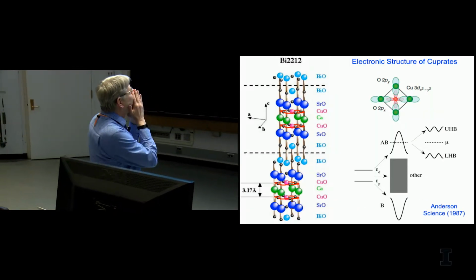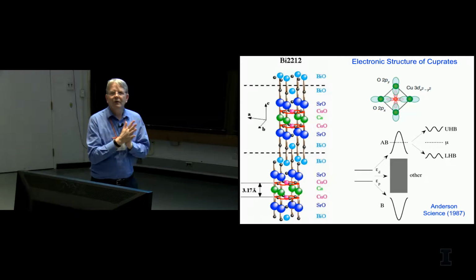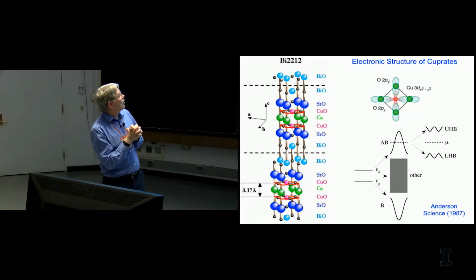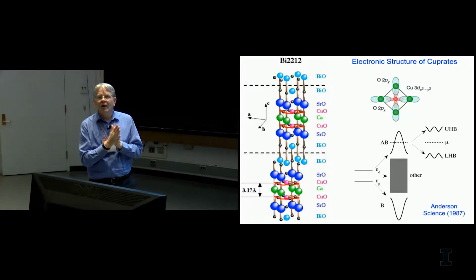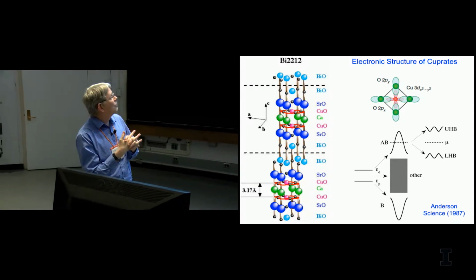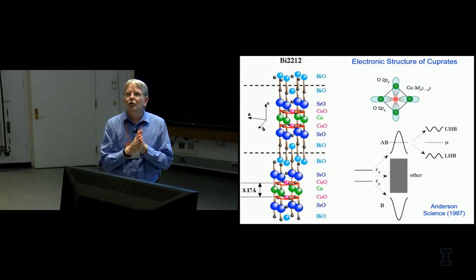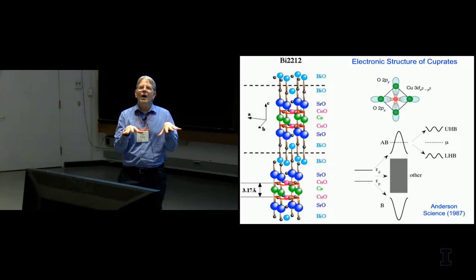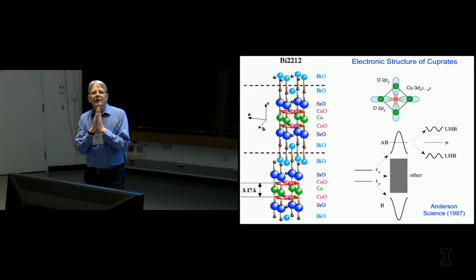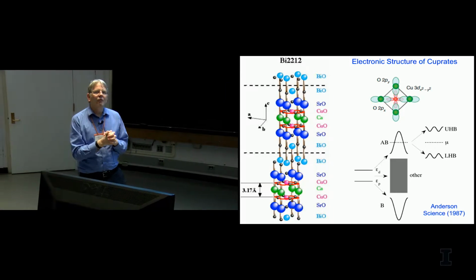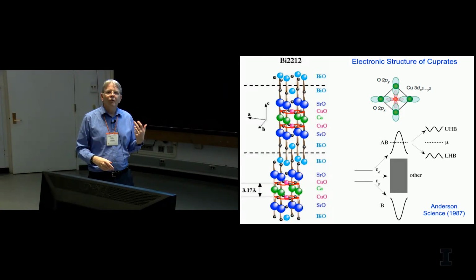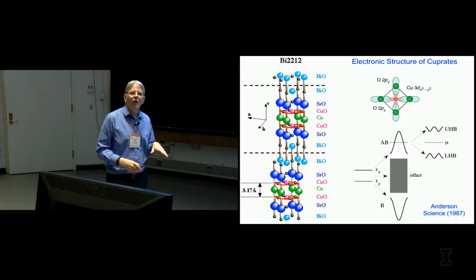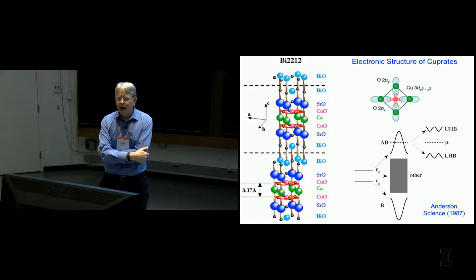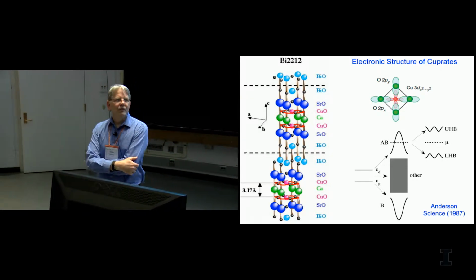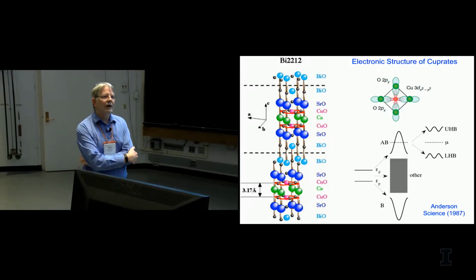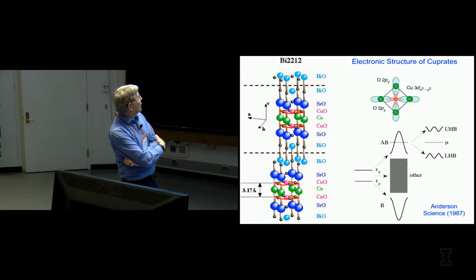So in some sense, cuprates are actually relatively simple from an electronic structure perspective. You have x squared minus y squared copper d orbitals hybridized with oxygen p orbitals. And this is what makes cuprates sort of unique. The oxygen p and copper d orbitals are almost degenerate. That means that you have a lot of covalency involved, and because of this, doped carriers typically are mobile because of the amount of oxygen admixture. And this is what makes cuprates different from other transition metal oxides, where you typically get polaron formation.